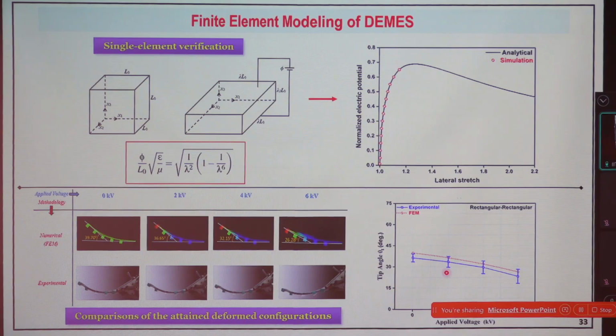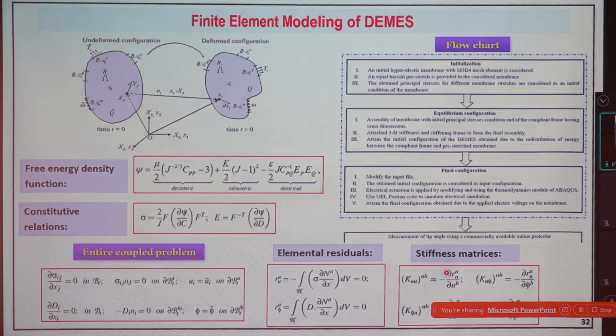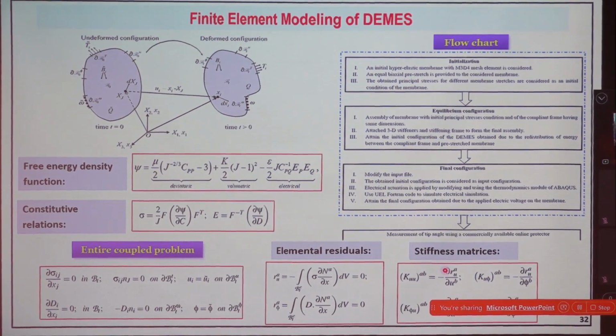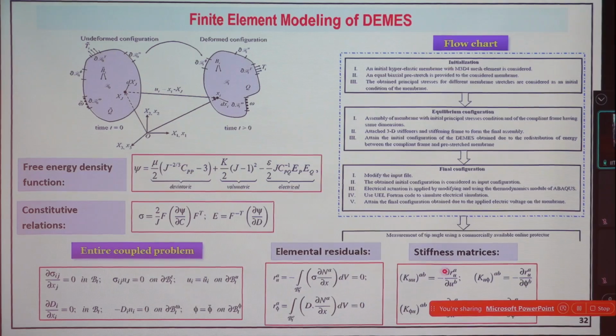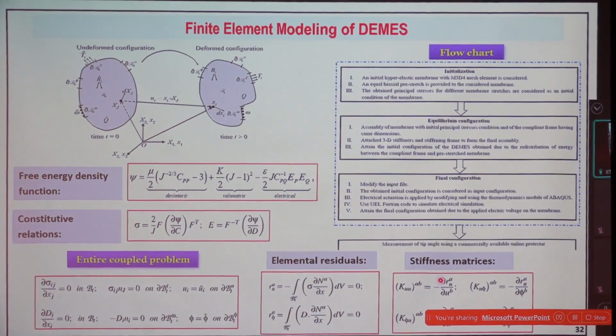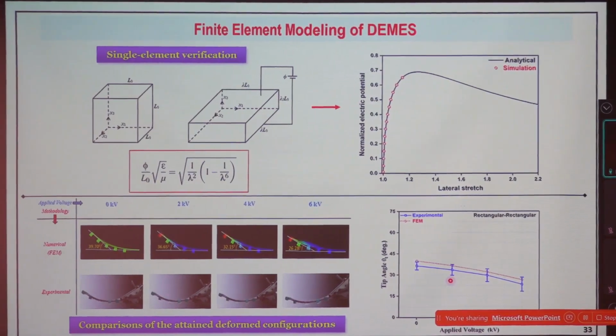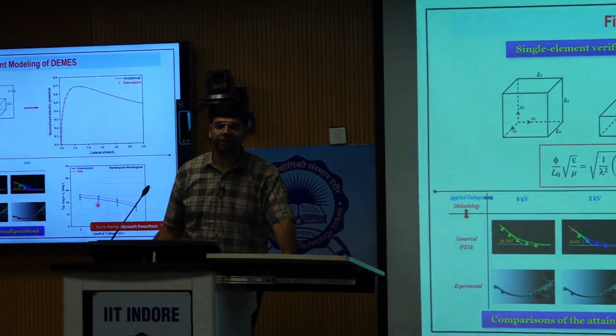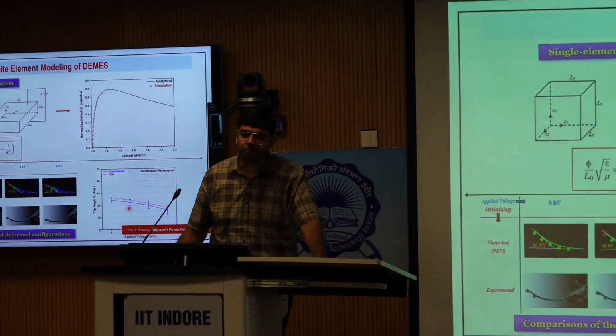External environmental condition is there. But if you see in the model carefully, have I considered the viscoelastic effect here? I have not considered the viscoelastic effect here. It's a simple hyperelastic model. But our VHB tape that we are using, I have already told you, exhibits strong viscoelastic behavior. So the angle obtained by actual experiment has the viscoelastic property, but in the model, we have neglected the viscoelastic behavior.